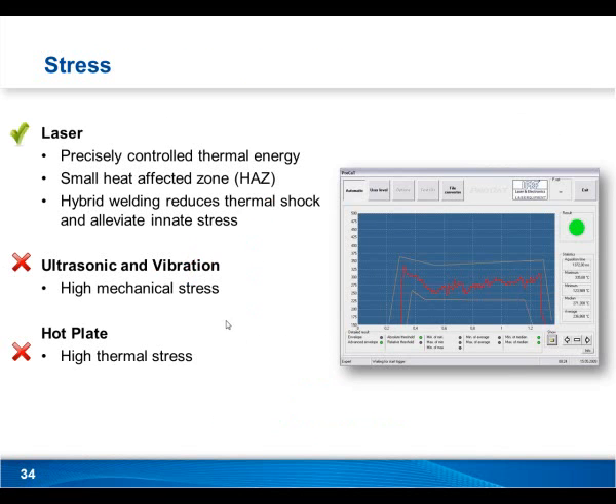Back into our comparisons, stress plays into durability like I mentioned on the first slide. Laser has precisely controlled thermal energy, so the heat affected zone is very small. And when you start to weld with mechanical methods, ultrasonic and vibration, and even hot plate, you tend to get a larger heat affected zone. So you're going to be adding a lot of undue thermal stress to the parts, and in some cases mechanical stress, and again that can cause durability and joint failure over time.